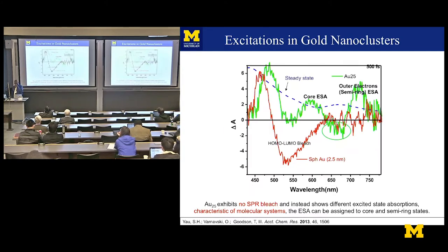However, in the case of clusters, that didn't happen. Okay, and so here again is the big particles in the red, and the blue is actually the absorption spectrum of the cluster, just to show you. And look what happens. Instead of seeing a bleach, you actually see these excited state absorptions. And this is the green, okay? We thought that was interesting. So there's no surface plasmon bleach in the case of these metal clusters. And you can see the excited state absorption out in this so-called semi-ring region.